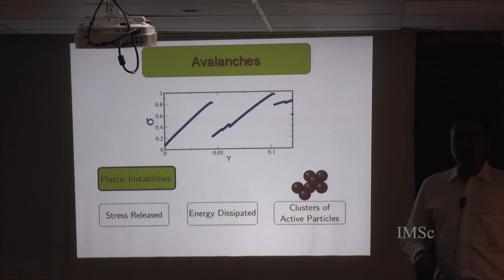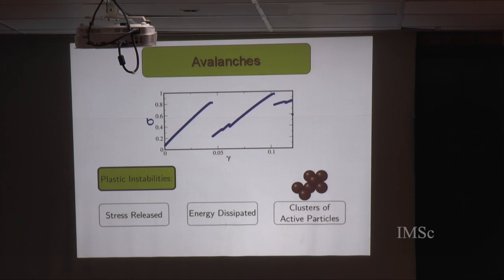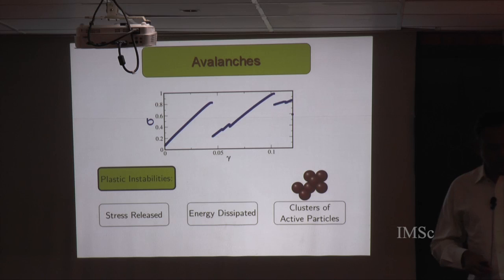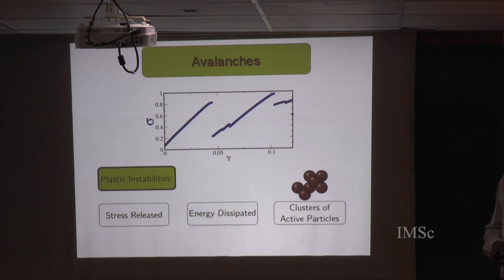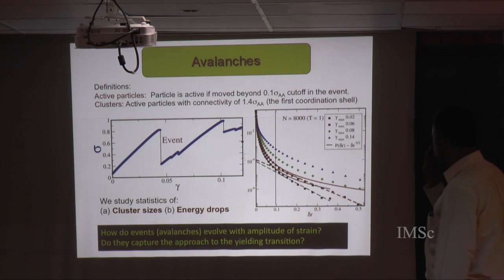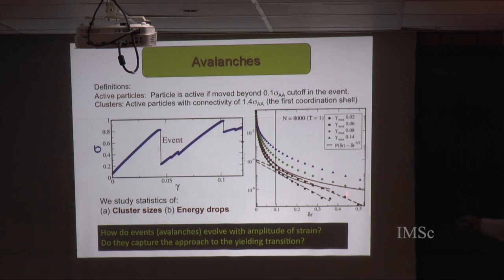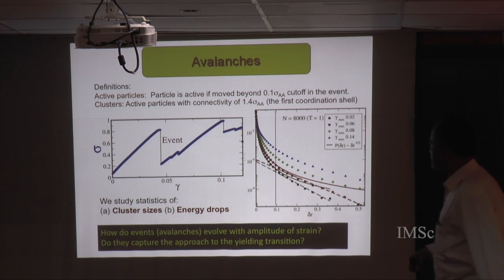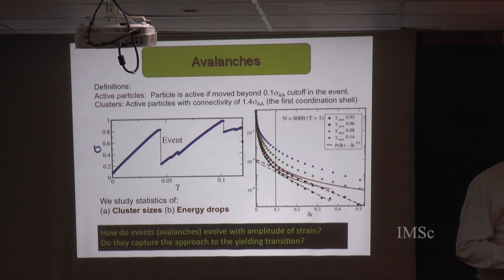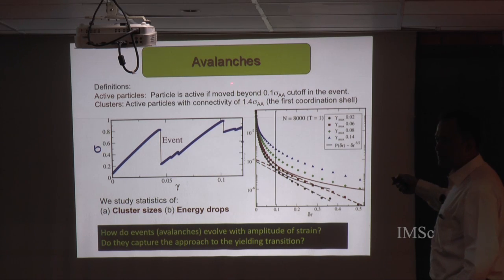By analyzing the displacement fields in the system, we identify a set of particles which we call active particles. These are the ones that undergo plastic deformation during one of these events. If you look at the distribution of displacements of all the particles, you find something shown here for different amplitudes of strain. Focusing on the black curve, this distribution can be separated into two components: a power law distribution for small displacements, followed by an exponential tail.